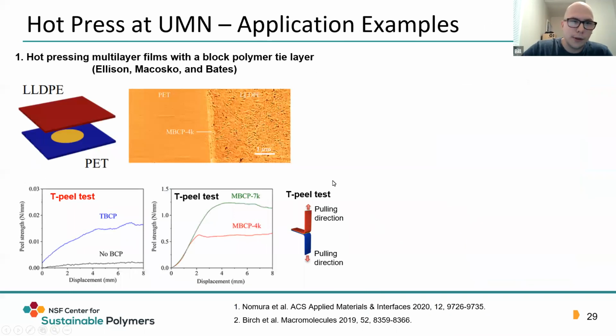A specific example of what's been done here is the use of a block copolymer to act as a tie layer between two incompatible polymers, where we see a substantial increase in adhesion between the two phases with this inclusion of the block copolymer that kind of entangles with both phases and ties them together.